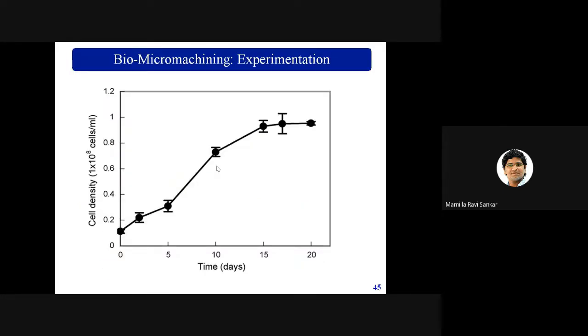So you can see that with respect to time, the cell density is increasing. As we normally observed in our studies, the maximum cell density will be at 21 days. So that is what we have reported, beyond which it stabilizes to a certain extent and then falls.